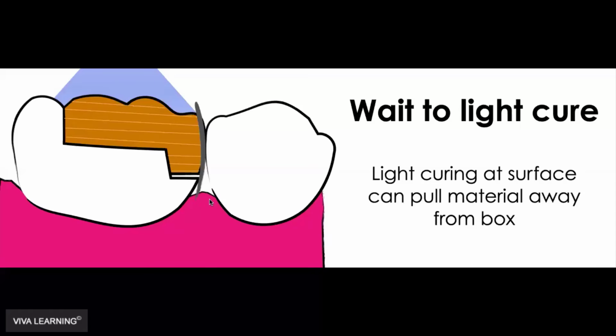Chemical cure is slower, so there's more time for molecules to align to resist shrinkage stress forces, as opposed to curing with the light very quickly, where things have to arrange themselves very quickly and might not form an ordered arrangement, such that they start putting shrinkage forces on your restoration and on the tooth preparation. So the clinical trick there is to insert it, wait 60 seconds, and then hit it with the light.